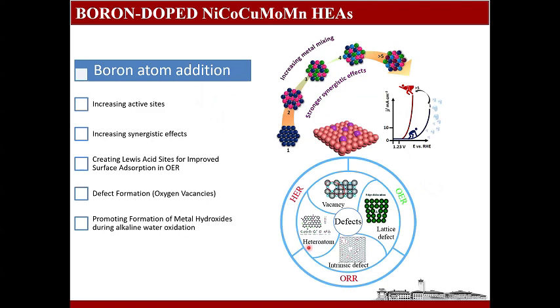And then we introduced boron into the high entropy alloy structure, because the size of boron is small, and boron might go either into the interstitial sites or might substitute some of the atoms in the high entropy alloy structure. So the boron atom addition might increase active sites. Of course, it might increase the synergistic effects. It might increase defects actually. It may create some Lewis sites for improved surface adsorption of the oxygen evolution reaction. It will produce defect formation, especially if it is introduced into the interstitials.